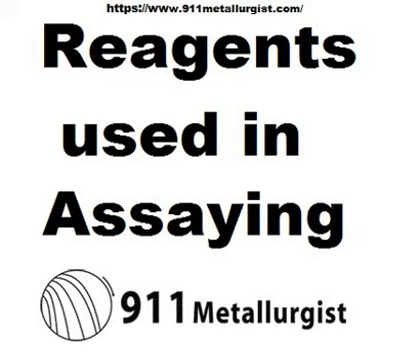Mixed with hydrochloric acid, fluorspar may sometimes be used instead of hydrofluoric acid. Calcium carbonate, CaCO3, is precipitated in a pure state by ammonic carbonate from a solution of calcium chloride. It is used for standardizing; in the impure state, as marble or limestone, it is used in the preparation of carbonic acid. Calcium hydrate, or lime water, is used in testing for carbon dioxide and in estimating the amount of that gas present in air. 100 cc of water at 15 degrees centigrade dissolves 0.1368 grams of the hydrate, Ca(OH)2, and hot water dissolves still less. Milk of lime is slaked lime suspended in water. Cobalt nitrate, Co(NO3)2·6H2O, is used in a 10% solution for the detection of oxides of zinc, aluminium, etc., on ignition, with which it forms characteristically coloured compounds.